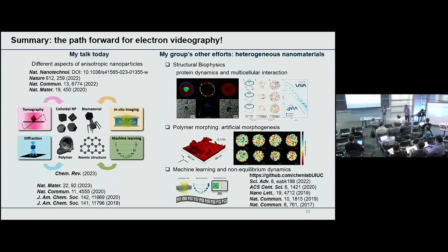In other words, for all the 4 growth modes I'm talking about, if you think about the system thermodynamically, they will prefer a very smooth surface. It's really because kinetically, in order to achieve a smooth surface, you need the building blocks to move very quickly. Sometimes that's not a requirement that you can satisfy. Also, that motion of the nanoparticles needs to be put into the context of the flux of the particles. That's why we have those parameters as the coordinates of the growth modes for the phase diagram.